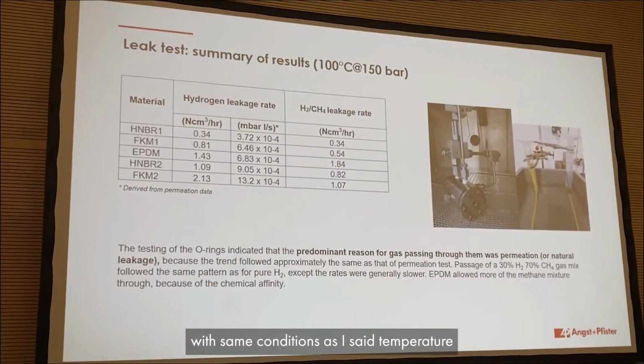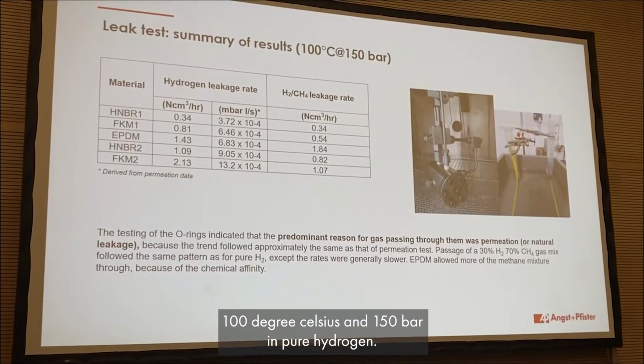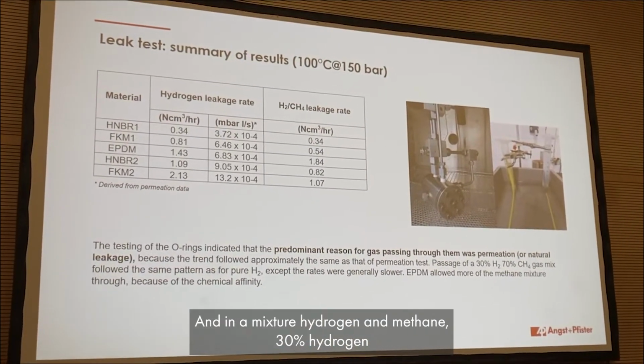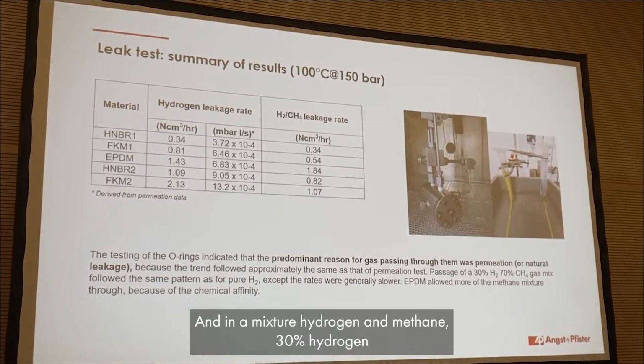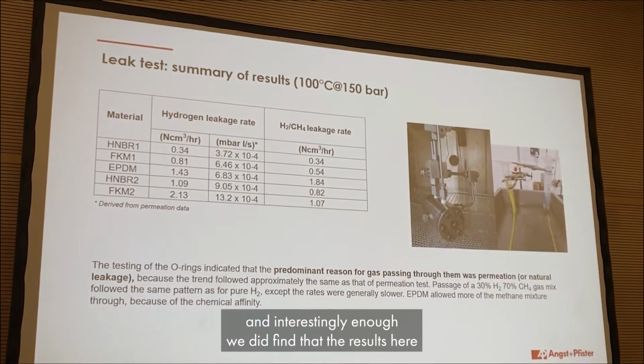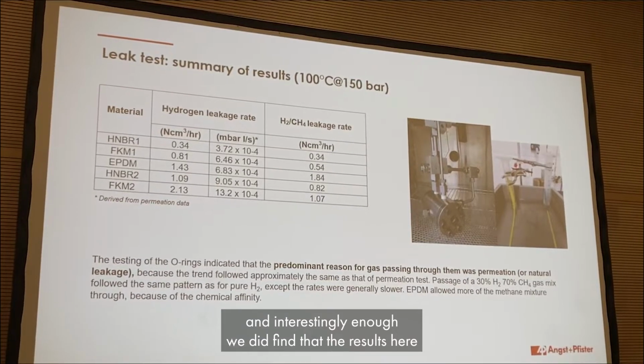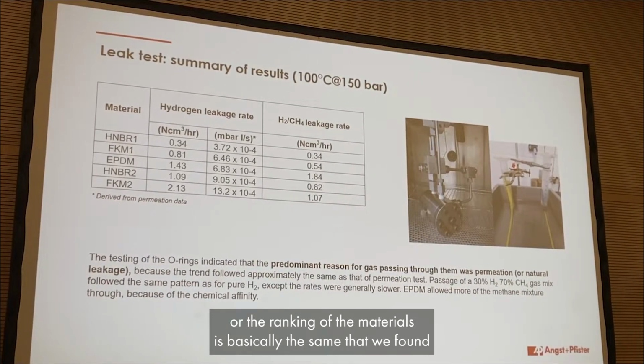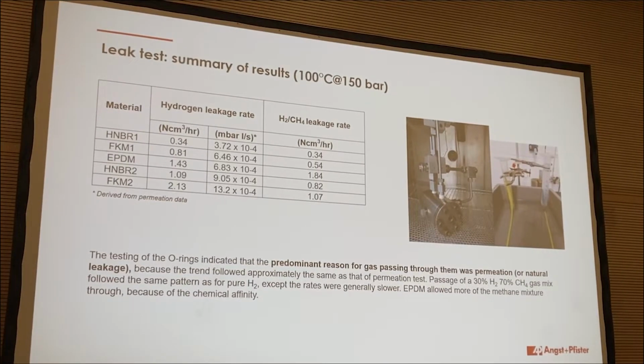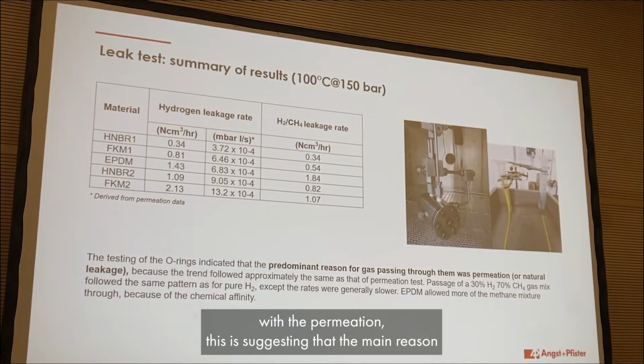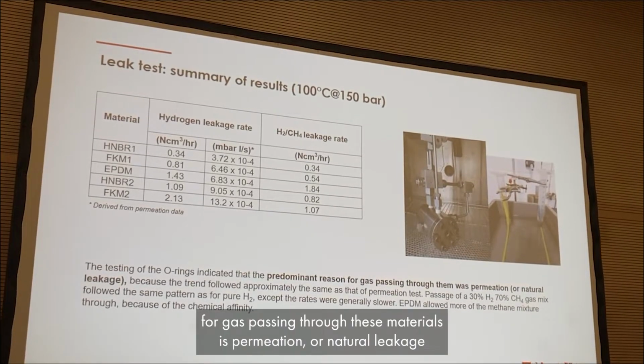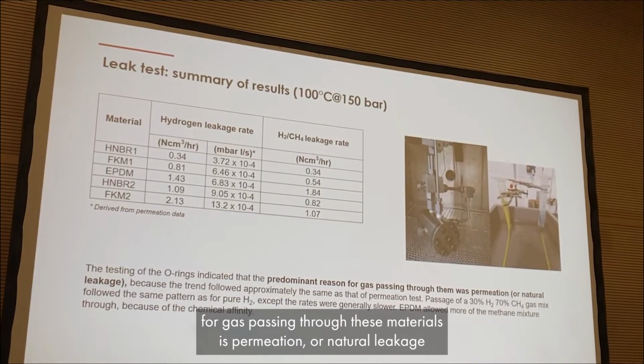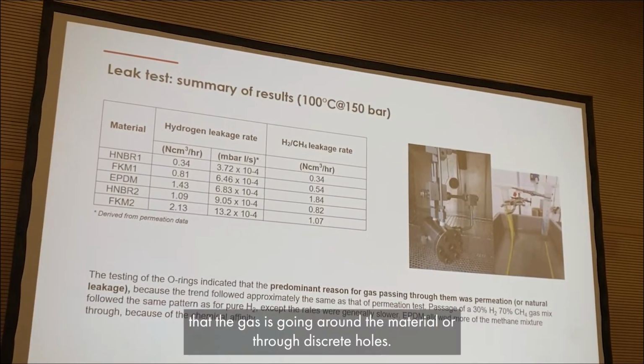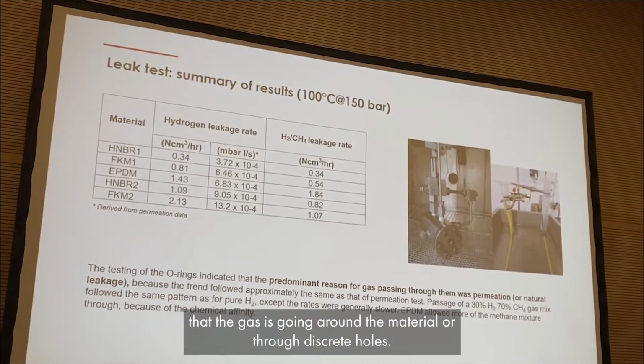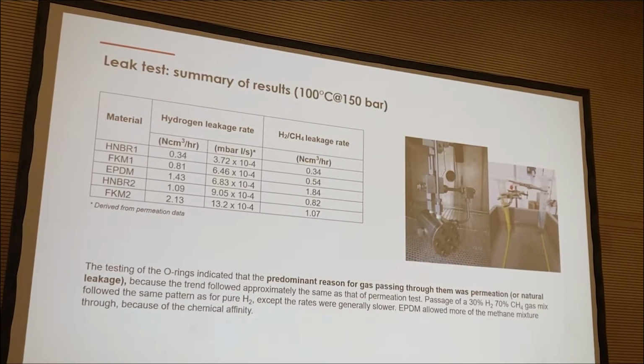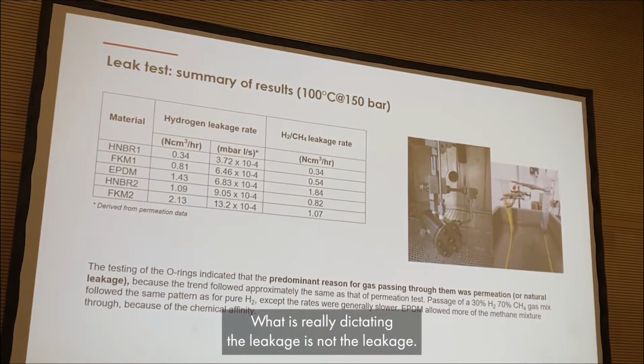Same conditions, as I said, temperature 100 degrees C, 150 bar, in pure hydrogen and in a mixture of hydrogen and methane, 30% hydrogen. And interestingly enough, we did find that the results here, or the ranking of the materials, is basically the same that we found with the permeation. This is suggesting that the main reason for gas passing through these materials is permeation or natural leakage. It's not that the gas is going around the material or through discrete holes. So what is really dictating the leakage is natural leakage.